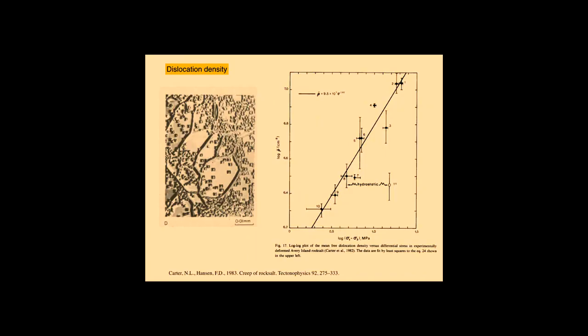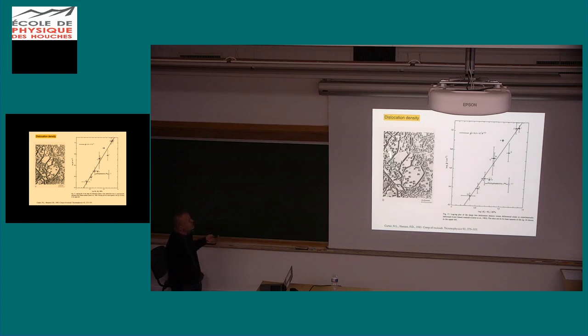The dislocation density was also measured using this etch pit technique, and this is a famous paper from 1983 by Carter and Hansen. And the dislocation density also scales very nicely with differential stress, as expected. All this work from the American laboratories was, I think, inspired by the need to create a waste disposal site for nuclear waste. And of course, this has been a controversial but also very actively researched and discussed topic, the rheology of salt in the WIPP site.